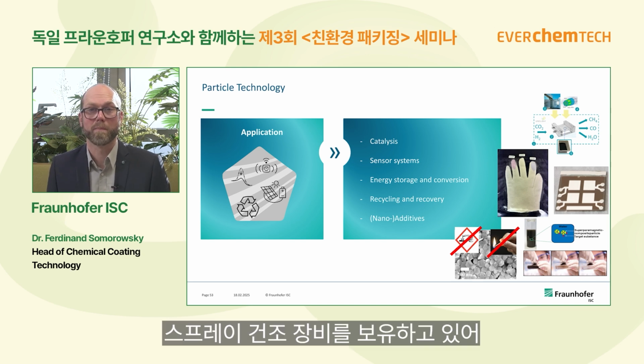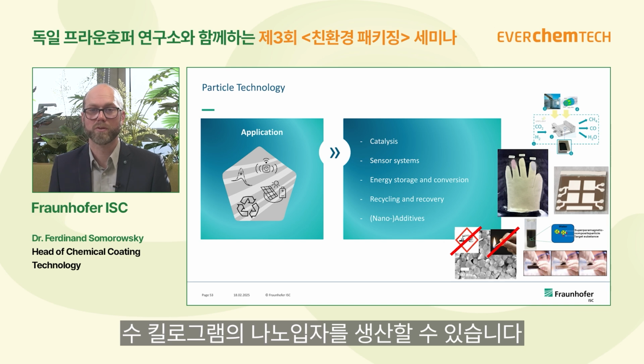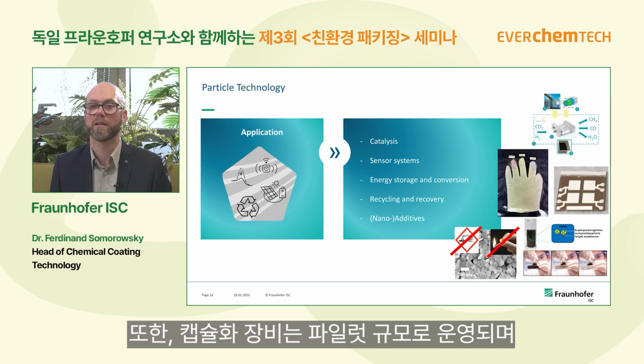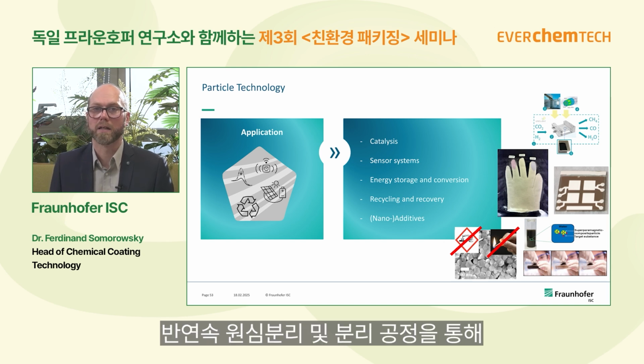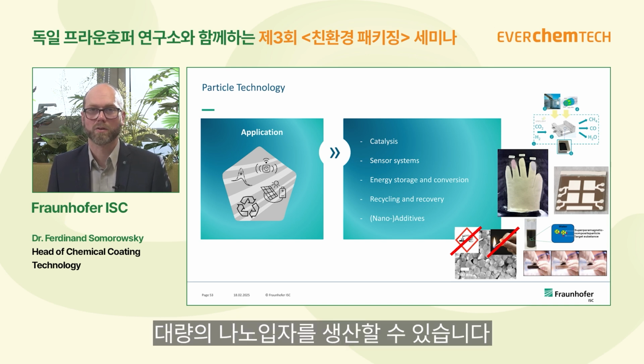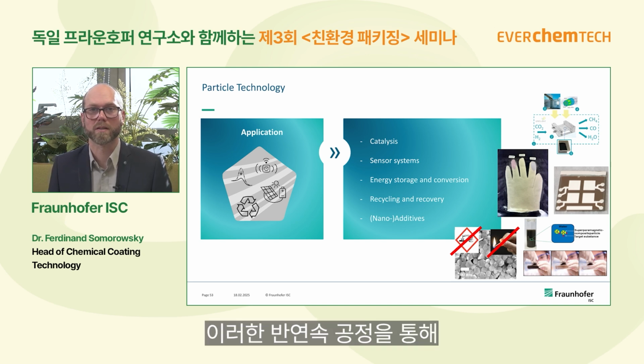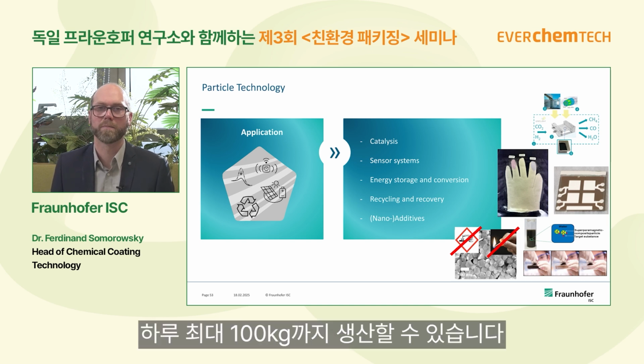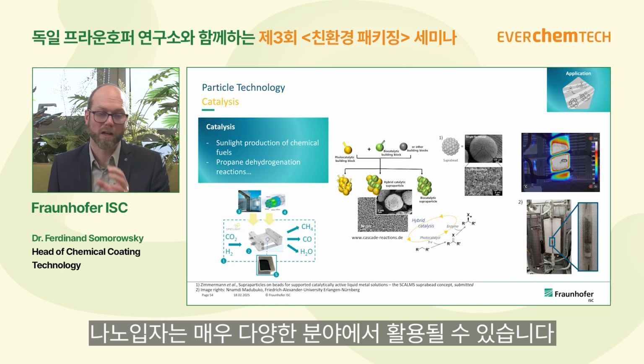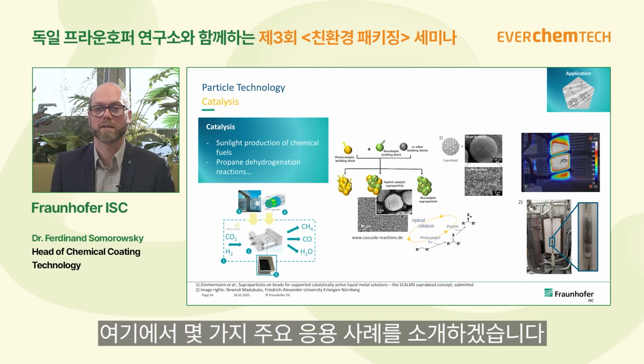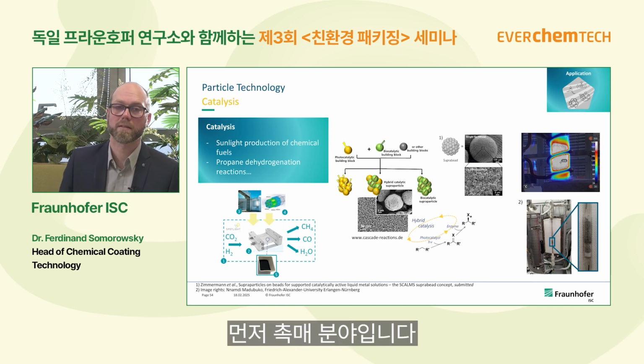We have spray drying equipment which can produce several kilograms of the nanoparticles. Also the encapsulation machine is a pilot scale machine, and the centrifugation is semi-continuous, so we can really produce several kilograms in a semi-continuous process, even around 100 kilograms per day. And then the applications, of course. These nanoparticles have a lot of applications. I selected several of them and would like to start with catalysis.